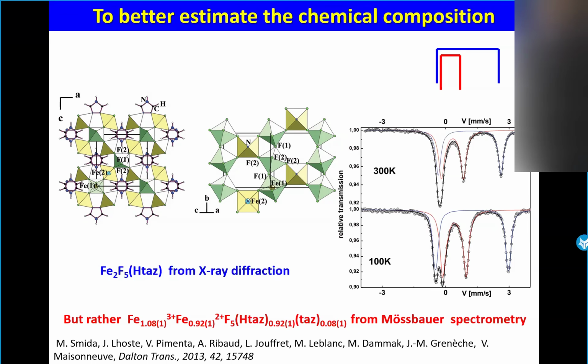Okay, because they have to do some neutron diffraction experiments, they made 4 batches to get enough sample for neutron experiments. And for each batch, I made a Mössbauer spectrum. And for all of them, 53-47. So it's not a perfect mixed system. And finally, of course, the interpretation was done with a kind of deprotonation of this molecule to satisfy the content of iron 3 and iron 2. So that means it was possible to better estimate the composition of the sample. And finally, they introduced this composition to fit again the X-ray pattern, and it was much better. Okay.